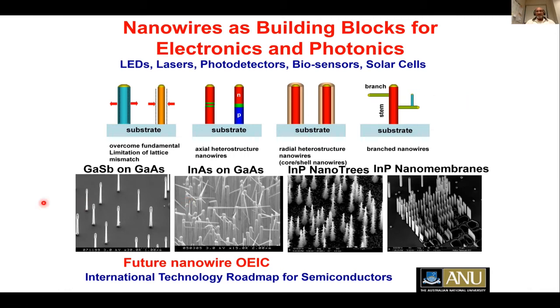So here are some examples we made in our own laboratory where we have shown that gallium antimonide nanowires can be grown on top of gallium arsenide nanowires. Despite large lattice mismatch, we were able to show that you can get atomically perfect nanowires of gallium antimonide on top of gallium arsenide. You can also make branched nanowires of indium arsenide on top of gallium arsenide. They could be used for cantilevers, scanning probes, and a range of applications.